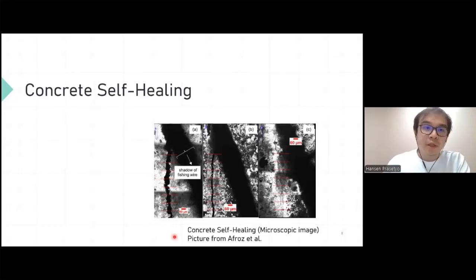So for example, we can look at this graph. This is from another researcher. She's from UNSW, but she also did her research in concrete self-healing. So on the first day, when the crack is induced, we can see that this crack is quite visible here, but on the third day, it started to heal up. And on the ninth day, the concrete is fully healed. The crack almost fully disappeared.